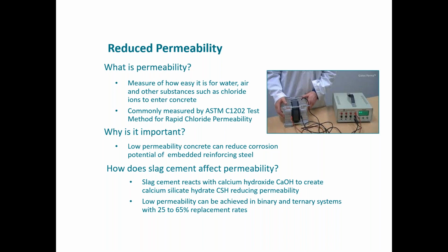But slag cement, considering that it does not have a drastic impact on the plastic properties of concrete, is a fantastic way to reduce permeability. The big thing about it is that there has been a change in mindset in the specifying community regarding the rapid chloride permeability test, which you're seeing here, a setup of the apparatus and the cells.